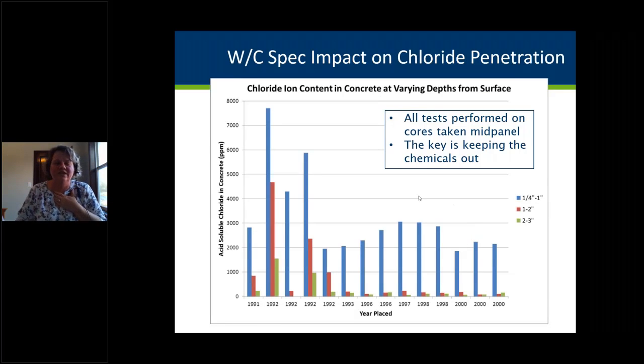And then chloride penetration. We took cores from the joints and we took cores from the mid panels. The cores where this data is from were taken from the mid panel. We did acid soluble chloride testing at 3 different layers in the mid panel cores. We cut the first 1/4 inch off. So then we measured 1/4 inch to 1 inch, 1 inch to 2 inches, and 2 to 3. And so the blue is that 1/4 inch to 1 inch surface. I do not have the line drawn, but right in here is the pre and post water cement ratio. This is kind of the transition area.